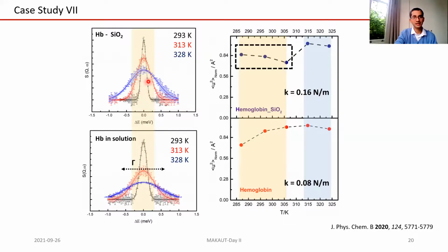It slightly broadens out if it is quasi-elastic, and by studying this kind of line width broadening, an important aside here: line width, or the broadening of spectral line shapes, is a storehouse of information. In this kind of experiment, if you study this, you can find out diffusion coefficients. I managed to find diffusion coefficients of protein in solution and protein inside silica nanostructures.